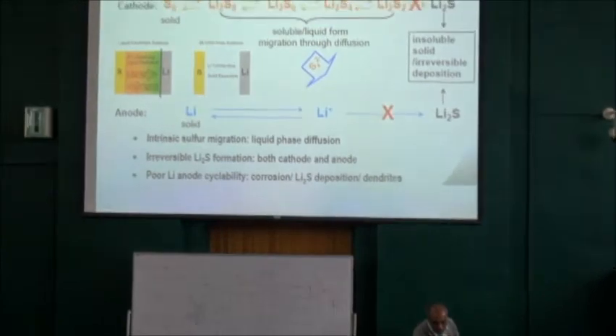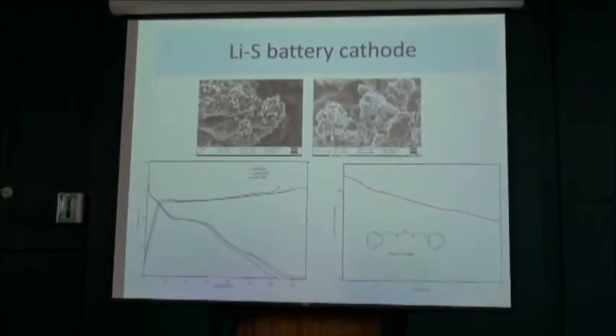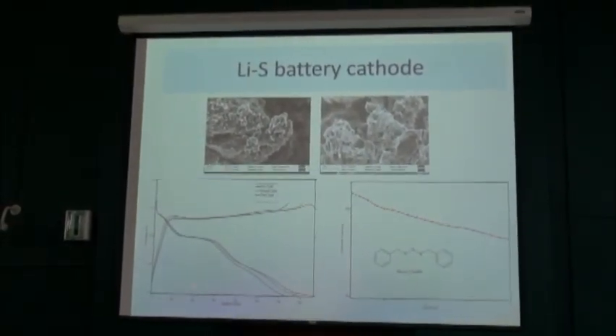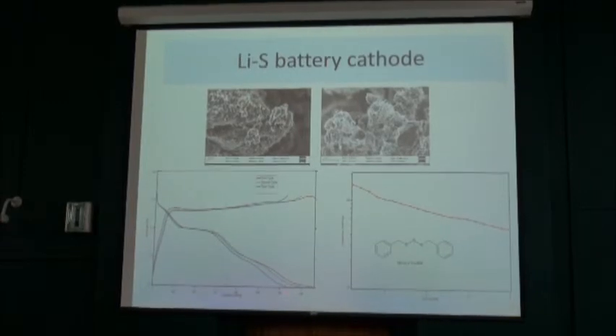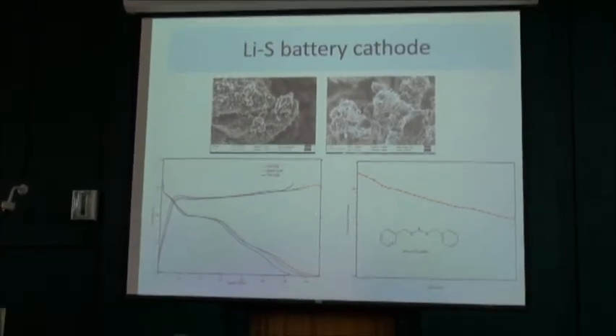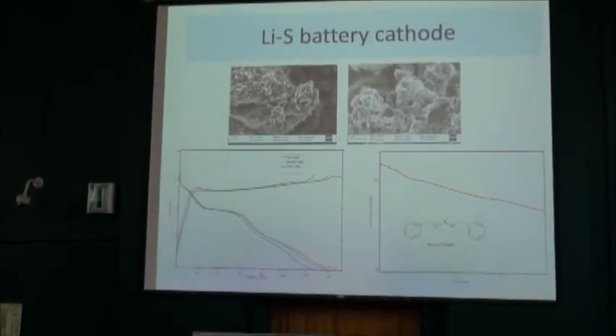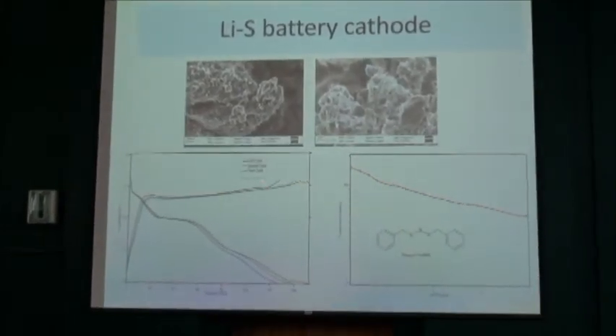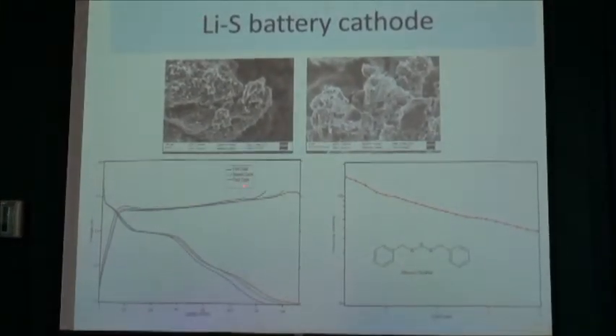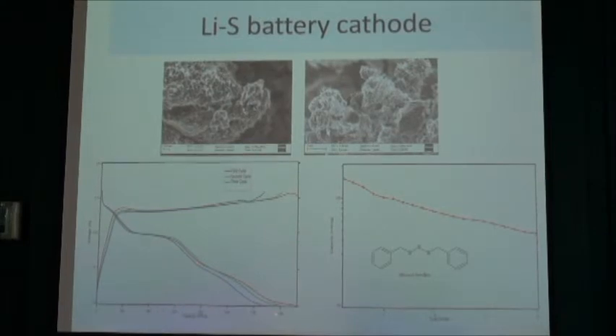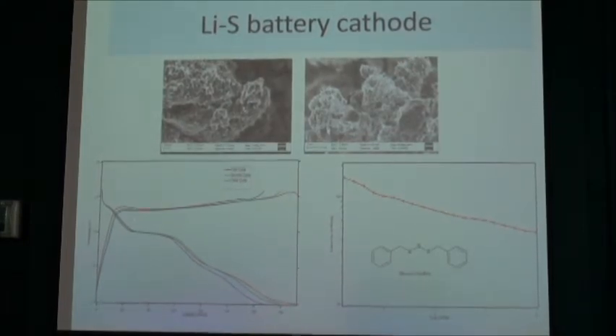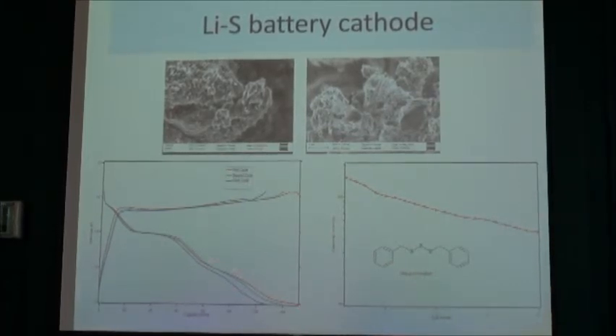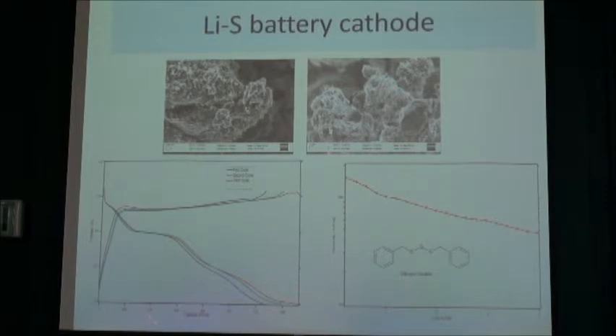So this is some of the results we have. You can see this is charging and discharging. Initially we had about 1600. I think this is after 10 cycles or something. Still it is fading, but very slowly. When we first did this, the first cycle had 1600, and after the second cycle it was almost down here.